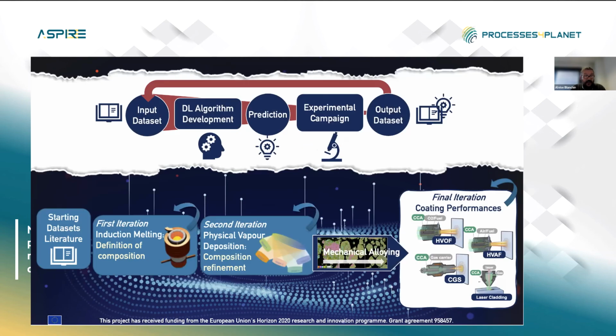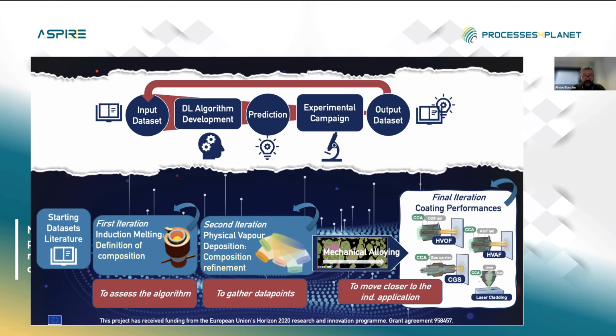But we cannot stop here. So after the first loop of activities on developing this deep learning algorithm, we checked the system by induction melting and then a second iteration by physical vapor deposition to eventually arrive at coatings obtained on real components. We use this approach because the first iteration is helpful in assessing the algorithm and that we are going in a good path. The physical vapor deposition allows us to get more data points around the main composition that we are interested in. And then the last step is the one closer to the application. The information gathered at this stage will be directly related to the possible application of similar materials with similar techniques, but to other use cases.